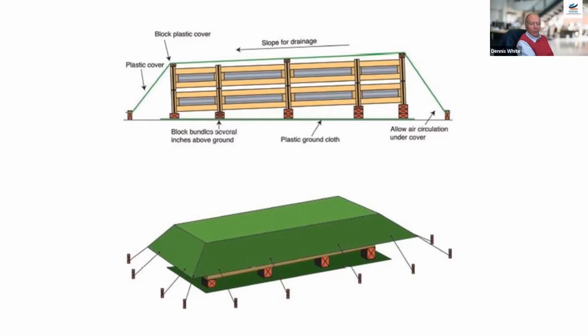And if you're going to be storing material on site for more than 10 days to 2 weeks, you really need to be constantly monitoring the state of that cover, that it hasn't sagged because something's been put on top of it, or it's got a hole in it after a storm, and then making it ineffective or possibly leaking onto the material underneath, and you won't discover it until you open the packs.